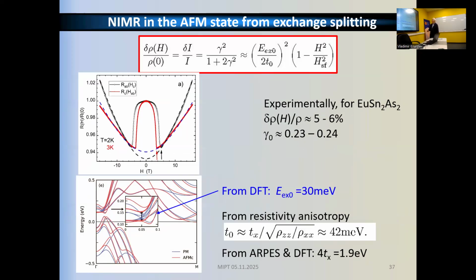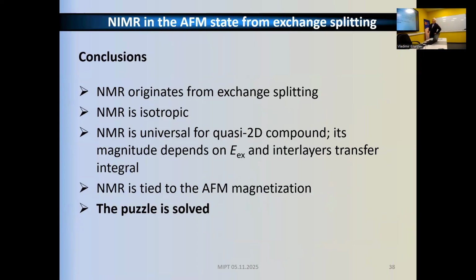We apply this to explain our effect, and we conclude that the negative magnetic resistance originates from exchange splitting, not from other known mechanisms, and it's isotropic. It's experimental proof. It's universal for 2D material compounds, and it can be greater or smaller depending on the exchange splitting. And again, I stress that the spin orbit interaction is much weaker. Just g mu B is an order of micro-electronvolts, or sub-millielectronvolts, and here 30 millielectronvolts.